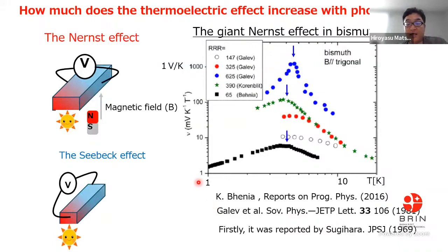And so the feature of phonon drag is a large Seebeck coefficient. Maybe this is the largest experimental result of phonon drag. This is not the Seebeck effect, this is just a Nernst effect, a transverse effect. But the amplitude is around 1 volt per Kelvin, a very, very large effect. Maybe this is a large sample and a very pure sample. If you use a large sample and a pure sample, you can get a large voltage by using phonon drag.